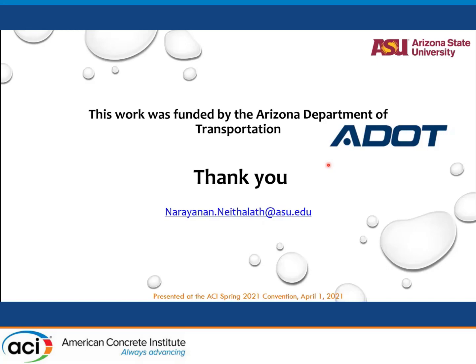Thank you. The other question is, do you have any mechanical property tests? Oh, we have plenty of those. I can do another three presentations purely on mechanical property tests. I just showed you the compressive strength alone. We have, like I said, more than 175 to 200 megapascal compressive strength. We have about 20 to 50 megapascal flexural strength. We have work that has recently come out on stress-crack width relationships. We have DIC studies on crack opening and fracture in these mixes. So yes, we have lots of mechanical results.